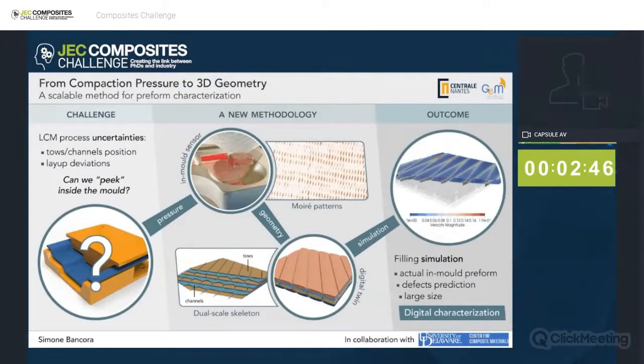Now, the interaction between layers originates some patterns on the pressure field, as you can see at the center of my slide. I like to see them as a signature, if you want, of the preform. And we can analyze these patterns by combining principles from Moiré theory with tools from image spectral analysis to extract and interpret the orientation and the spatial distribution of tows for every layer in our preform.